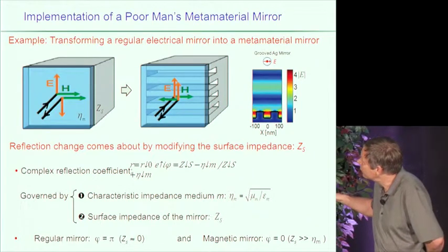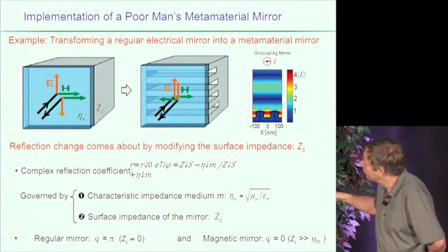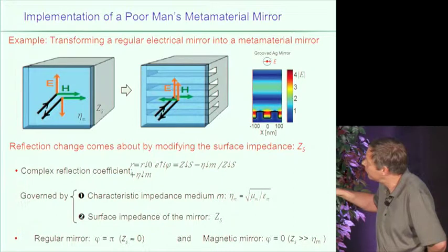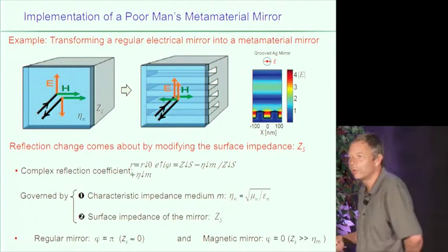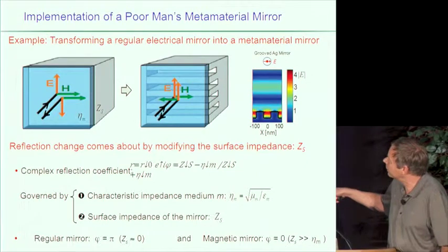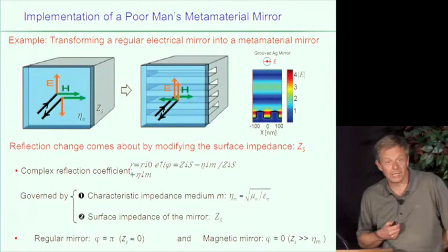And here you can see a simulation of a grooved surface here at the bottom, light wave coming in, and you can see now the first high standing wave maximum is right on top of these, what are in blue, these metallic teeth. So if I have a thin layer, it could be graphene or it could be a thin organic solar cell, I can tap into this high field to get the maximum light intensity.